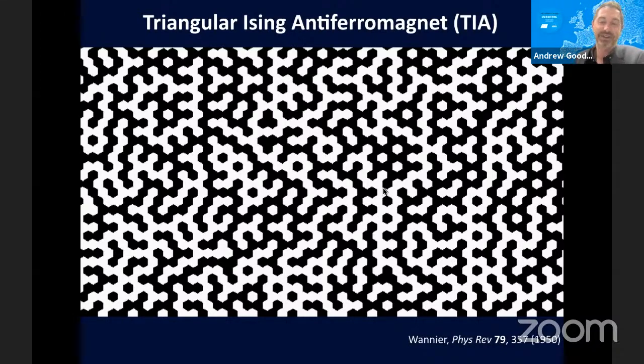But of course there may be cases, it is fair that we grow up thinking about functional materials as being ordered. So the statistical mechanics of many of these systems, including the one on the screen here at the moment, is well established, and these are thermodynamically accessible phases, for given model systems. Obviously, very often you have longer range interactions that will break these in real materials, and the ground states, if you go to the very lowest temperatures, would in fact very often be ordered. For many of the systems that I'm showing, there may also be kinetic trapping, but there's no universal sort of way of saying, oh, I'm going to favor one or the other across chemically very different sorts of systems.